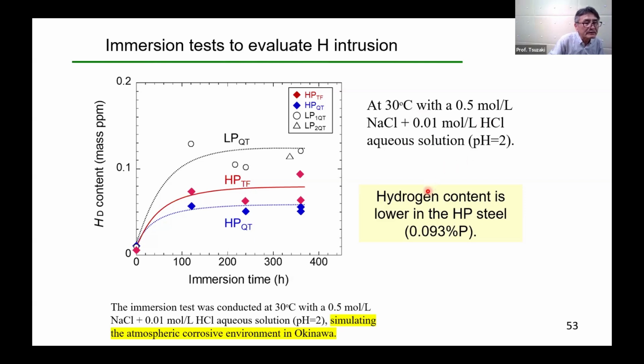The hydrogen content is lower in high P steel, 0.093% P, indicating that the P doping is effective to suppress hydrogen intrusion. I believe this is maybe due to the intergranular segregation of P.